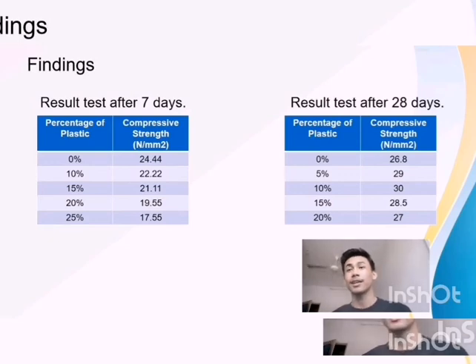At 28 days, the highest compressive strength is when we added 10% plastic into the concrete, as we get 30 Newton per millimeter squared, rather than the lowest one, which is the natural concrete that did not have any plastic added. The lowest is 26.8 Newton per millimeter squared with no plastic. So that's all for me for the findings of this article, replacement of fine aggregate with recyclable plastic in the concrete.